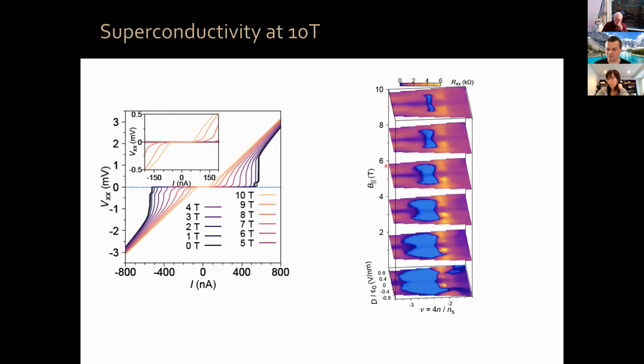We can study the strongest superconducting dome, the one between -2 and -3 holes per unit cell, okay? As a function, continuously, of displacement field and filling factor at different parallel magnetic fields, we see that it shrinks the superconducting region continuously, but it remains finite. So superconductivity exists in fields in excess of 10 Tesla.